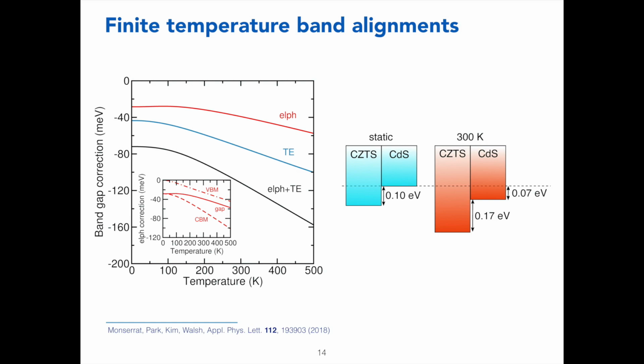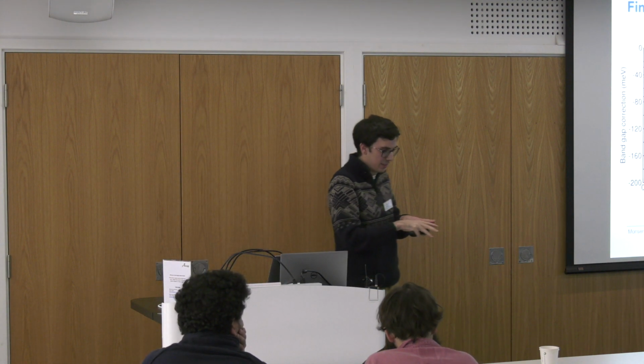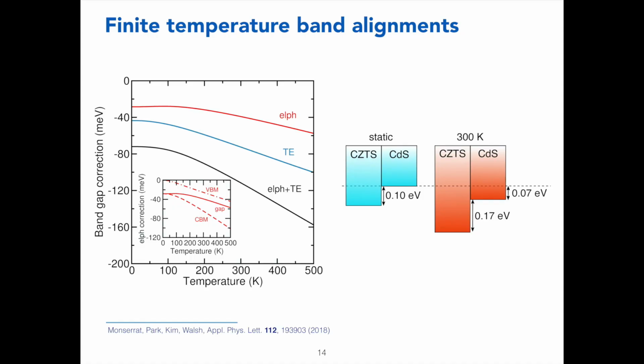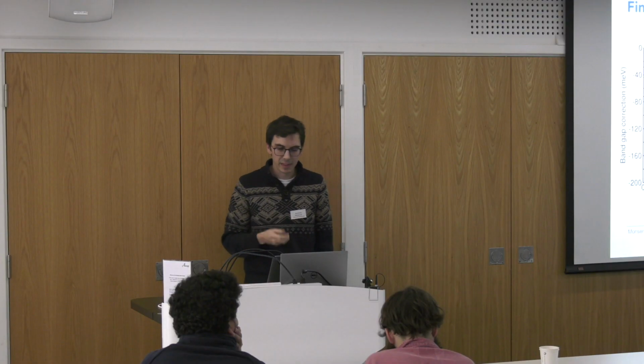And what we showed here by looking at the temperature dependence of the band gap, and something I haven't mentioned, is that not only do we have to include electron-phonon coupling to capture that, but also thermal expansion, because that's something else that happens in materials when you heat them up. Then the band alignments are actually relatively sensitive to this. And this is something that hasn't really been appreciated very much, at least in this community, but I think in general. And when one tries to design solar cell materials, it's actually worth thinking about the effects of temperature on these band alignments when you perform calculations to screen over candidate materials, for example.